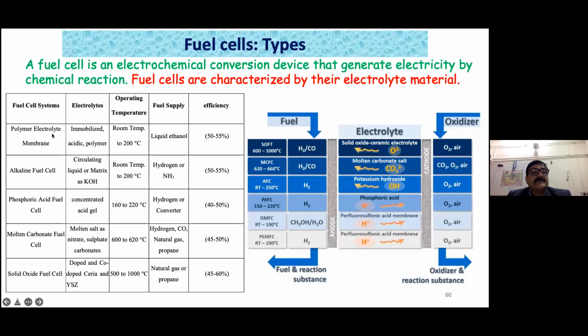The operating temperature for polymer electrolyte membrane fuel cell is from room temperature to 200 degrees Celsius. The alkaline fuel cell, room temperature to 200 degrees Celsius, phosphoric acid fuel cell 160 to 220 degrees Celsius, molten carbonate fuel cell, 600 to 620 degrees Celsius. This is the operating temperature, meaning you need to have this much temperature to operate. Okay, solid oxide fuel cell.